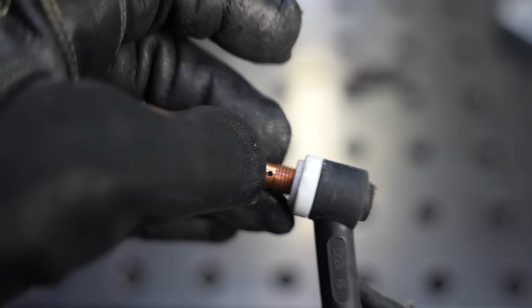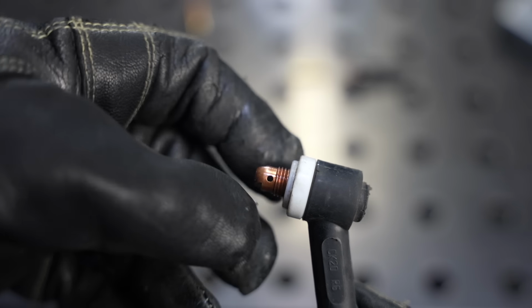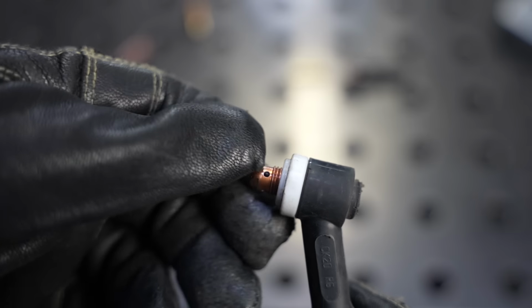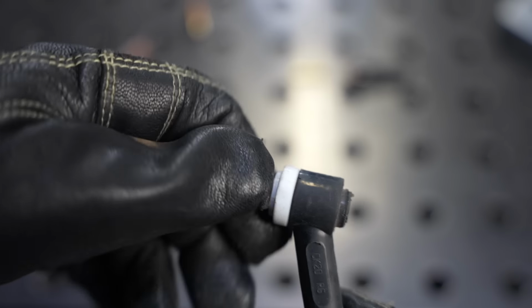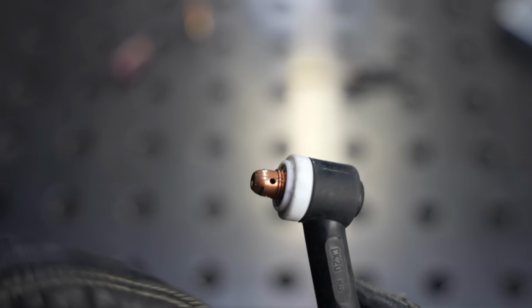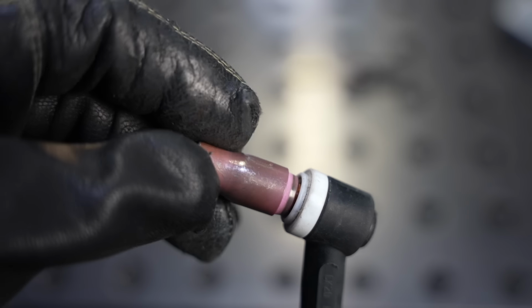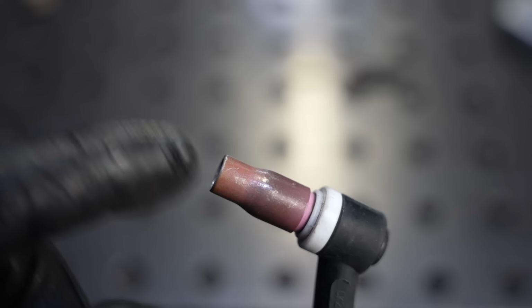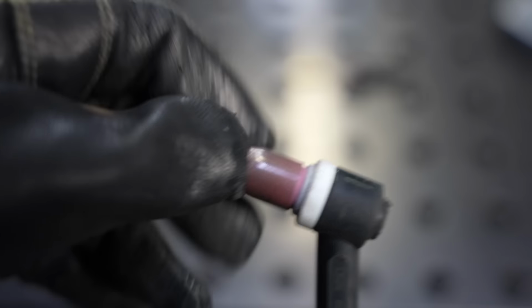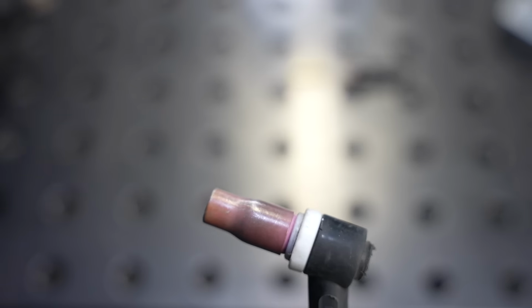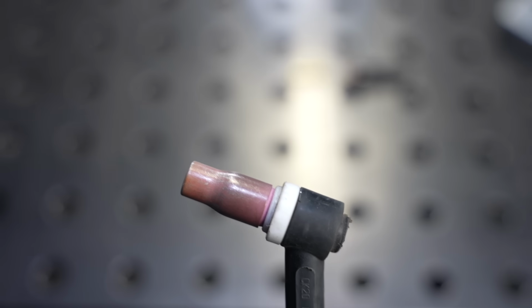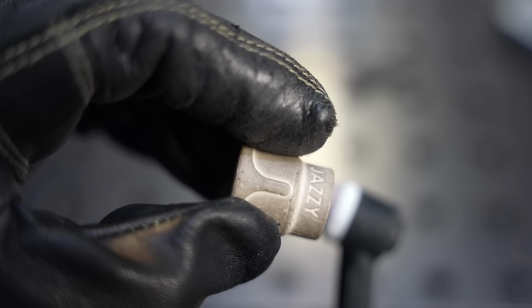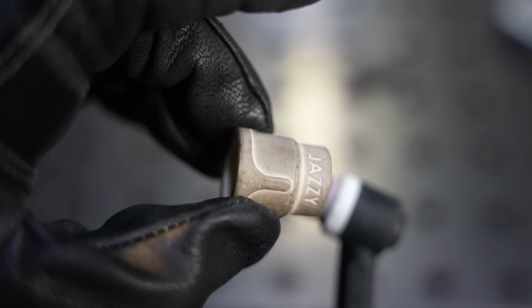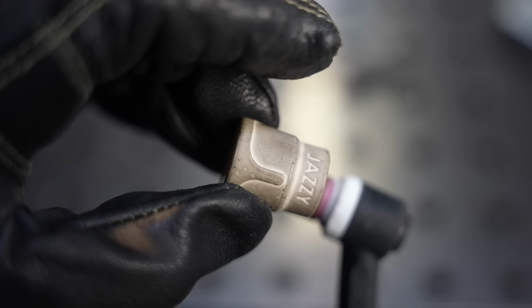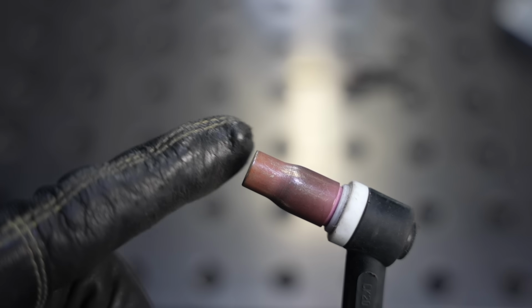I've seen excellent aluminum TIG welders that use either setup. It's really not the deciding factor. So just pick one when you're learning, and then once you get a little bit of time under your belt, try them both and keep using what you like. Now, as far as the cup goes, I use a smaller one around a number 5 to a number 7. And that's because it controls where the gas flow goes, which will control your etching band that you'll see in a little while. I see a lot of beginners throwing on a gas lens and a big cup like this, which I really like this cup on stainless steel and even carbon steel, but for aluminum, you're better off with a small cup like that.